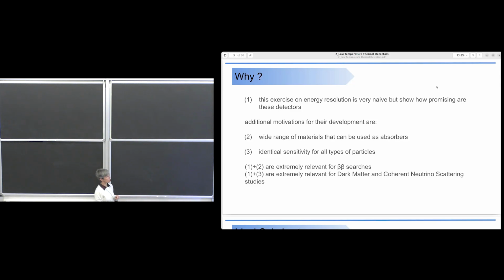While with almost all of those candidates, I can build a thermal detector. And then there is another property that is sometimes an advantage, sometimes a disadvantage. Whatever is the kind of mechanism that leads to energy deposition inside this crystal, I measure the energy deposition once it is transformed into heat. This is completely independent of the particle that is releasing energy.